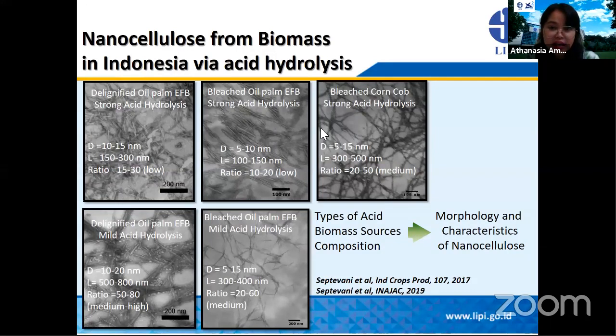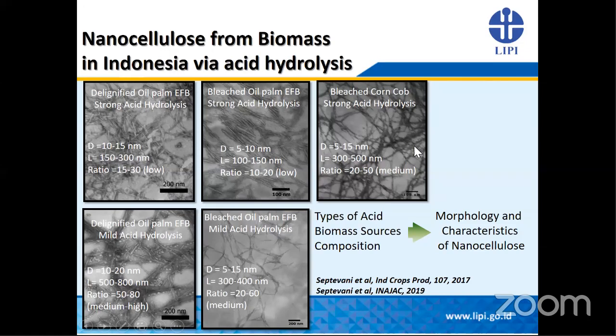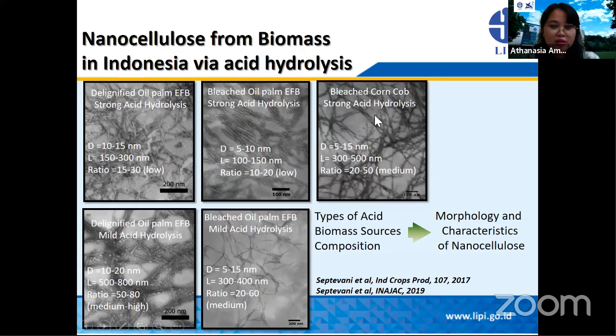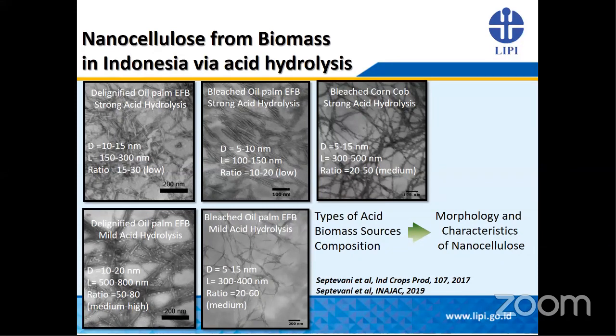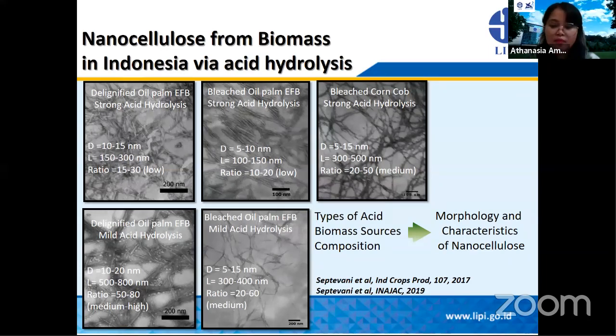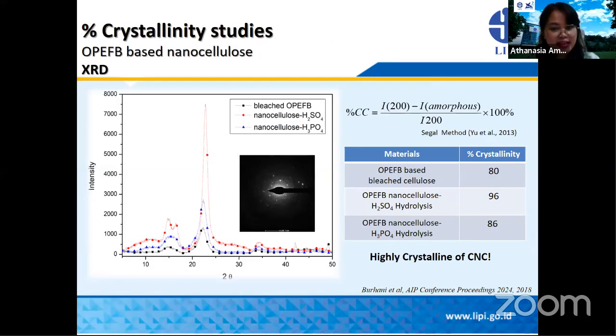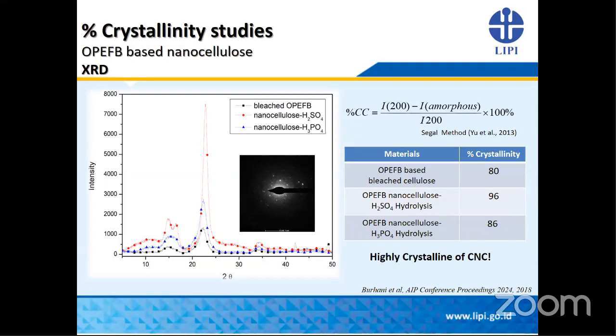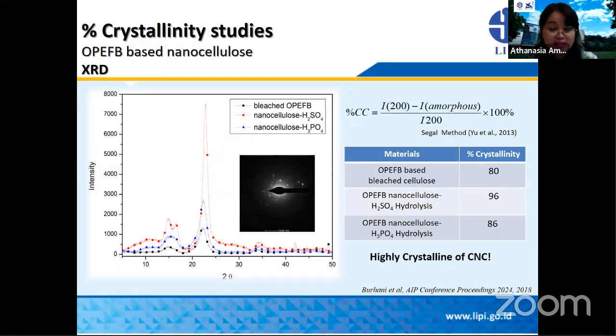It is also interesting to see that with strong acid hydrolysis, for example with the use of other resources such as corncob, even though we are using strong acid hydrolysis, it will produce long entangled fibers. So this result emphasizes that the biomass resources really play an important role in determining the morphology and characteristics, as well as the type and also the composition. So this is the crystallinity study. You see that the highly crystalline CNC is obtained from the strong acid hydrolysis compared to the mild acid hydrolysis.